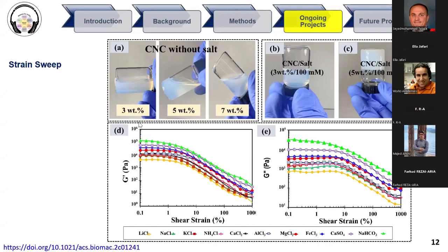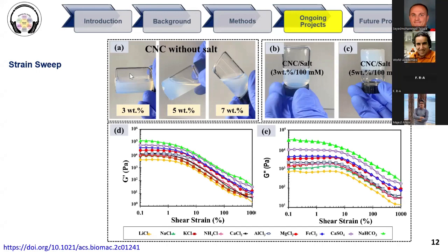This is so important because we need to run all rheological tests in the linear viscoelastic region. From A, B, and C, as I mentioned in my previous slides, we can see that whenever we add salt, we can increase the viscoelastic properties and have a strong gel. For example, if we tilt the vial, there is no flow. So this test was conducted just for finding the linear viscoelastic region, and by looking at the results, we can find that a shear strain less than 1 is the linear viscoelastic region. So we need to conduct our rheological tests in this region.